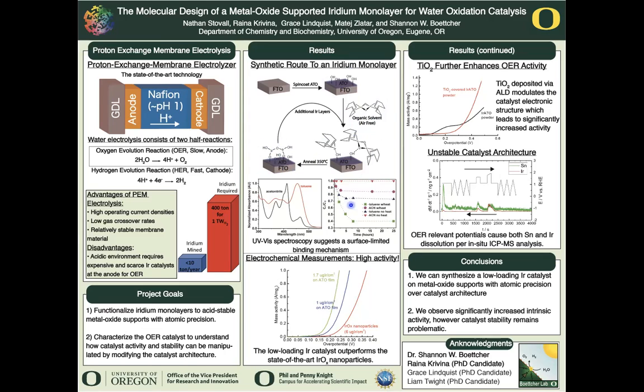And we also find that these hydroxyl groups limit the reaction on iridium. You see in this UV-vis data, the concentration of our dimer here eventually will level out no matter what solvent conditions we use, meaning that when this levels out, the reaction is stopped. And that gives us precise control over the atomic architecture of our catalyst. And interestingly enough, too, if you anneal and get hydroxyl groups again on the surface of your material, you can add additional iridium layers if you choose to do that.